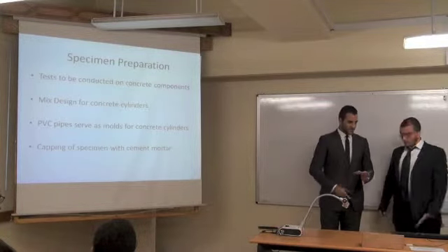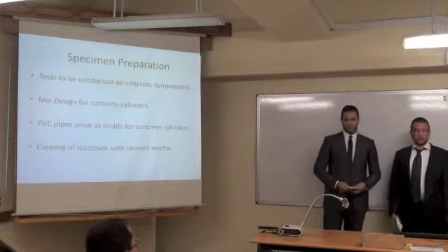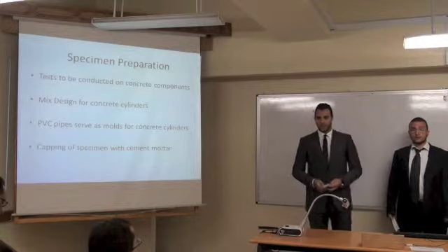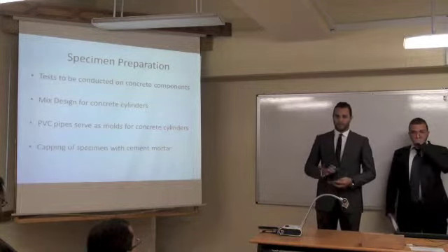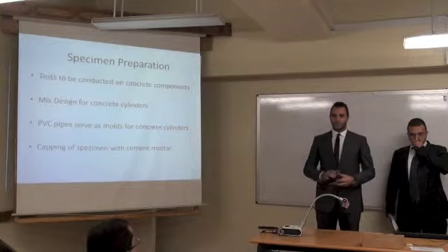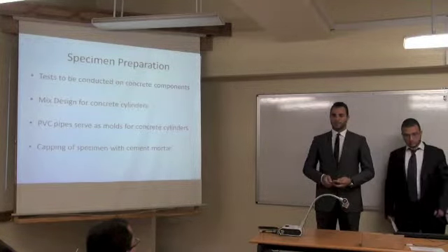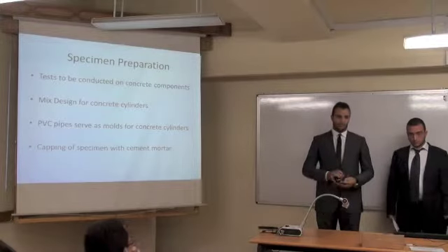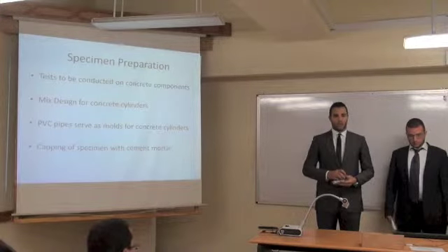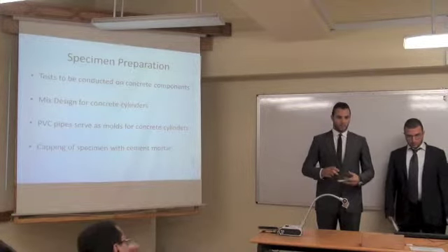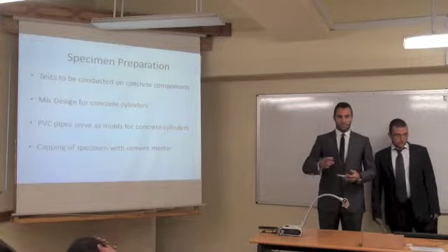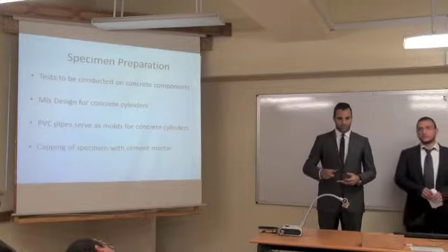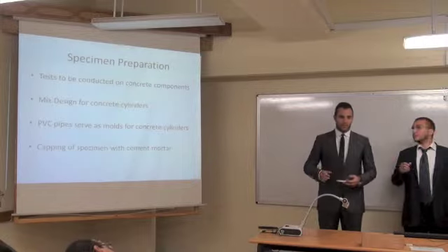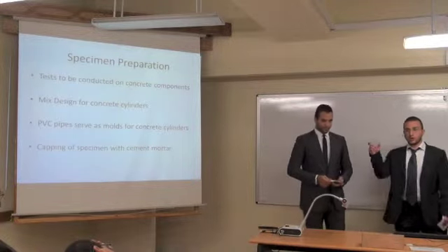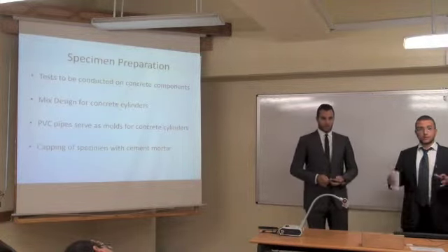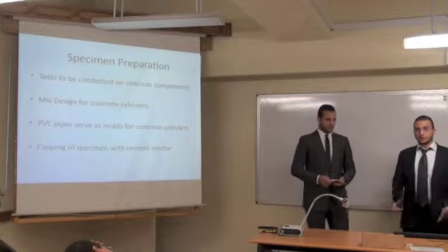Yeah, and we'll use the PVC pipes as molds for concrete cylinders. We'll use it twice. Once when we apply the compression on the concrete being surrounded with the tubes, and another time we'll use it to have the same volume of concrete, but without having the tube around. We'll have the tube cut vertically from both sides, 2 sides, so that you can remove it easily. This is for the plain specimen that won't be confined by the PVC tubes.